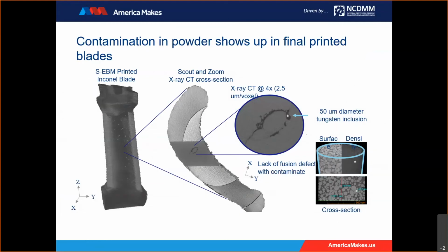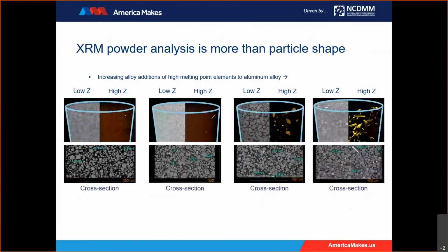So we went back and we took a look at the powder that was used to build these samples, and we found these tungsten particles in the powder. And I guarantee you that if the researchers had seen this in the powder, they wouldn't have printed these blades, because it turned out to be an issue where the filament that was used in atomization was contaminating the powder. So XRM powder analysis is more than just the shape.